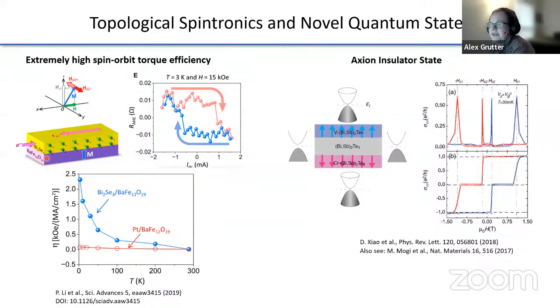What people are interested in doing is switching a magnetic material, in this case often it's a magnetic insulator, by flowing a current through your topological insulator. And so you can actually achieve very high efficiency magnetic switching. And this is one of the things that Peng was showing, is that as you cool down and the topological surface states more and more dominate the conductivity of your topological insulator, you get really large efficiency gains and can massively outperform, say, switching via platinum.